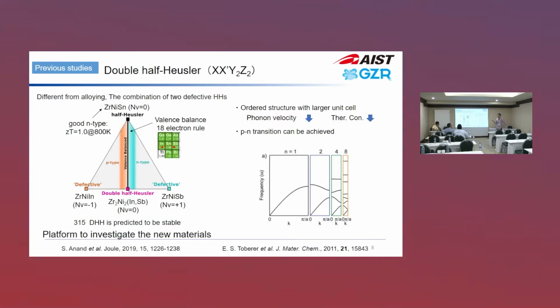Recently people found these double Half-Heuslers, which come from double perovskites, so twice the chemical equation, and you can have a larger unit cell if you have an ordered structure. The conventional ternary Half-Heusler zirconium nickel tin is 18 electron balanced, with 18 electrons from these three elements. But the defective Half-Heuslers like zirconium nickel indium and zirconium nickel antimony have 17 and 19. If you mix these two, you can design a double Half-Heusler that sustains the 18 electron balance with semiconducting behavior.